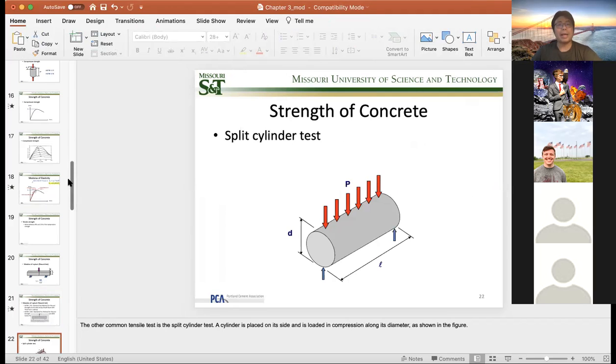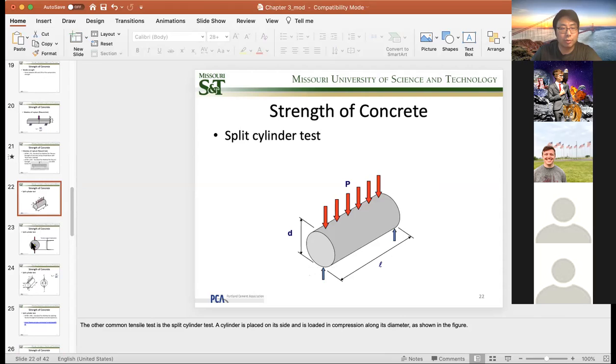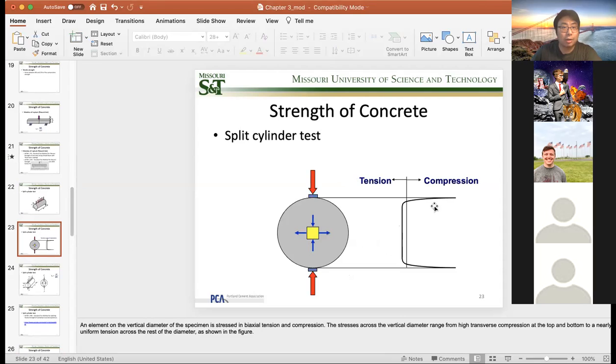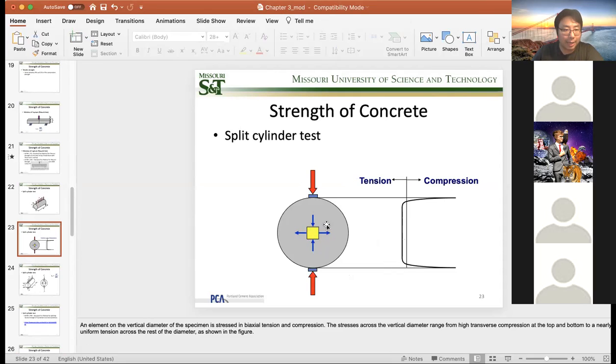Now for the tensile strength, there's another way to get it faster, using the same cylinder. We apply a line of pressure on top of the cylinder, supporting the two ends of it. Through this experiment we also get the strength, but the stress distribution is not uniform. When we apply pressure on the top and bottom, there will be concentrated compression. Afterwards, we generate a tensile stress in the middle of it. When the tensile stress in the middle reaches its peak strength, it busts.